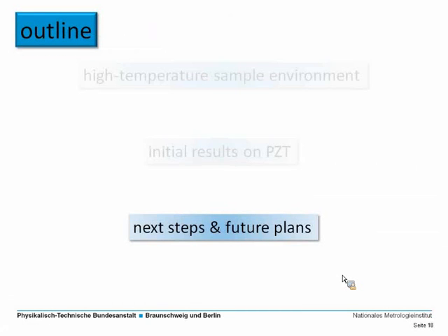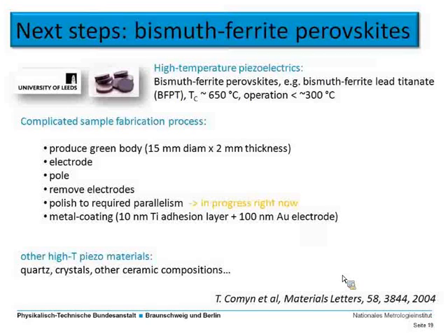So I want to show you some next steps and future plans that we have. One thing is we're going to look at different piezoelectric materials, in this case bismuth ferrite perovskites. This is in close cooperation with the University of Leeds, who are also engaged in the METCO project. They are specialized in fabricating those materials, and the first candidate we are looking at is bismuth ferrite lead titanate, which has a Curie temperature of about 650 degrees centigrade, so operation should be possible up to 300 degrees centigrade.